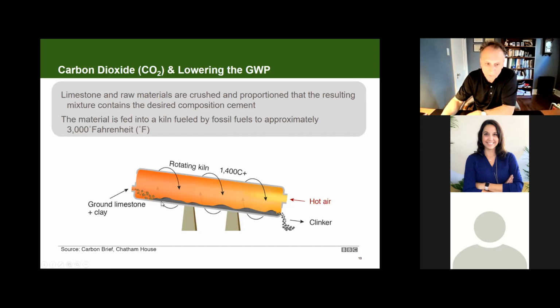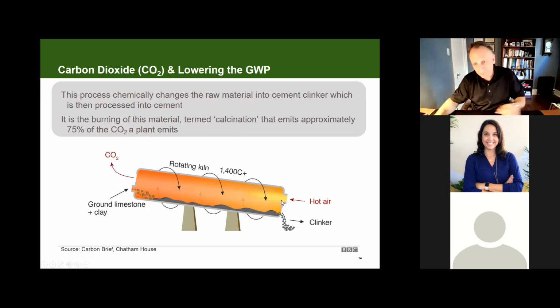So we introduce ground limestone and clay at one end of the kiln. At the other end of the kiln, we have our flame going. And then out of the kiln comes that clinker, which is what we ultimately are going to grind into our cement. So the problem, for lack of a better word, is that what comes out of this kiln is our CO2.